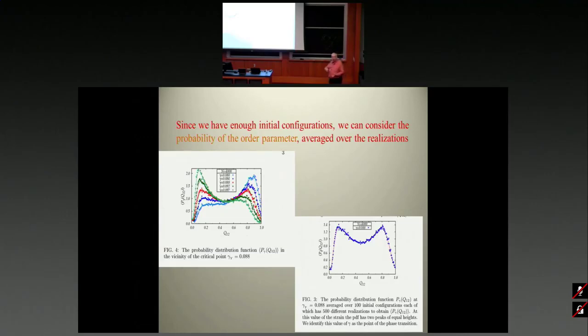Now, if you say I have a PDF, if you had a free energy, it'll be the logarithm of it, then you have a region of flatness here. It means that you have a flatness in the derivative of the free energy with respect to the order parameter. That's a spinodal point, like the one that you have in usual first-order transitions, like the liquid-gas, etc. So when you just go to the limit of the availability of two phases, and you just go to the one phase.